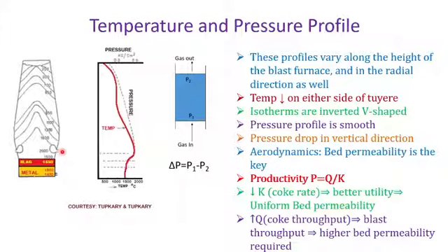We know that the blast furnace is a counter-current reactor where continuous reduction of iron ore takes place, and metal, meaning the pig iron or hot metal, and the slag are tapped at regular intervals. The reduction of iron oxide is a high temperature phenomenon, and the thermal requirement of the process is met by burning of coke and the enthalpy of the blast, along with the combustion of blast additives, if any are added.